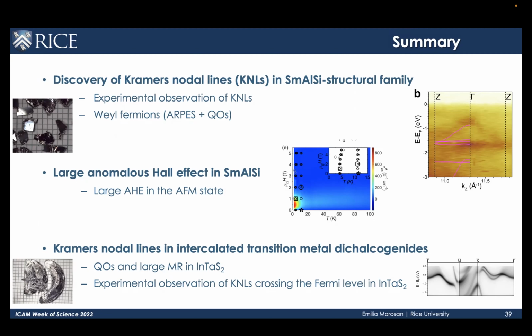Is the susceptibility looking like a Curie-Weiss temperature dependence, up to what temperature? Up to about 150 Kelvin, and then some crystal field comes in, yes. Do you know what the effective magnetic moment is? I don't remember. Do you know what the valence of the samarium is in this? 3+. Not mixed valent. Because we don't have a large range of Curie-Weiss-like behavior from which I can determine the effective moment very accurately, the bit that I can fit tells me that it's 3+.